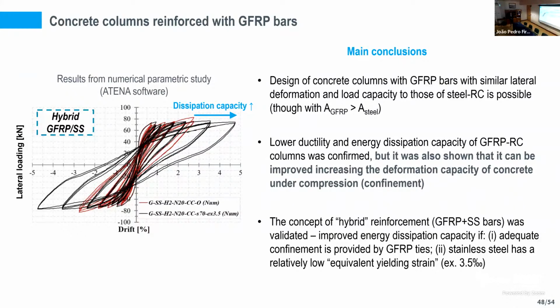But for that, we need two main conditions. We need to provide appropriate confinement for the concrete under compression, and we need to adopt a stainless steel bar that has a relatively low equivalent yielding strain, so that we can explore the yielding stage of these bars before the GFRP bars fail. Typically, they fail under compression in this application.